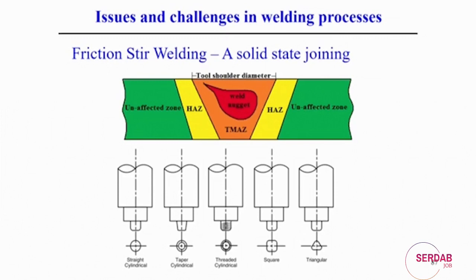In the friction stir welding process, two components are simply joined by stirring of plasticized material. So, the temperature should be controlled so that it stays well below the melting point temperature. Frictional heat is generated and the plasticized material is mixed, and it finally makes the weld joint. So, a typical characteristic of this solid state welding process is that it creates a nugget zone, and that nugget zone is basically defined by certain temperatures, along with the thermomechanically affected zone, heat affected zone and unaffected base metal.